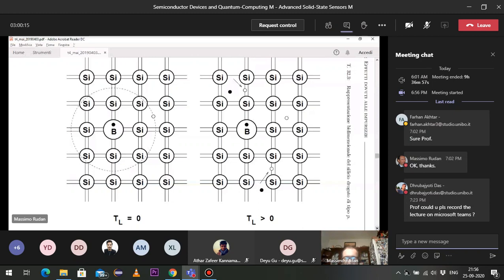So you see, in a semiconductor, we have two dual possibilities. When we use boron, like in this figure, we enrich the valence band of holes. Holes are, as you remember, positive carriers. So we also call boron a dopant of the p type because it provides extra positive charges to the valence band.